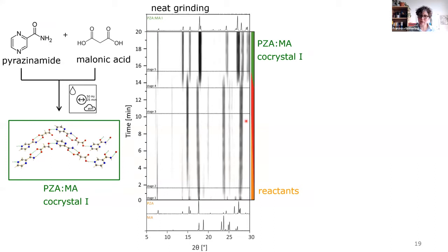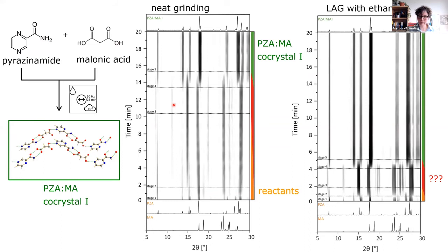So we have more stages in between, and this red area, you can see here is a tiny reflection coming up that we don't see in the final compound. This is actually another polymorph of this cocrystal. And you can see that it only persists for 2 minutes in its pure form, and also under liquid assisted grinding conditions here with ethanol, it persists for 2 minutes.